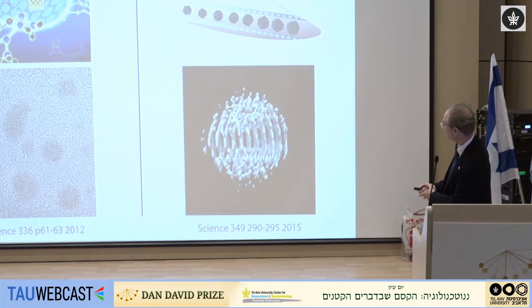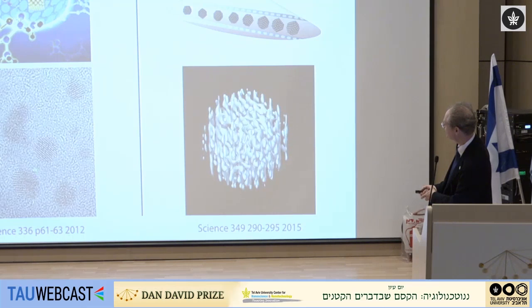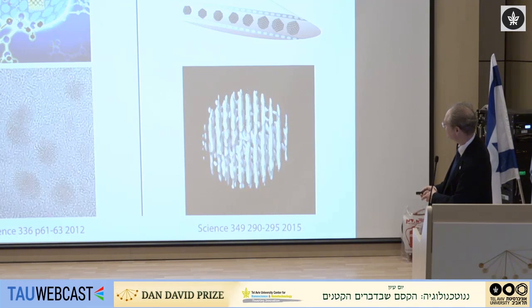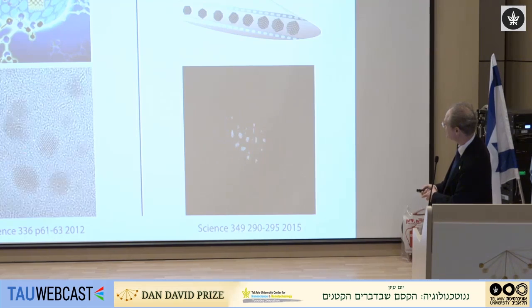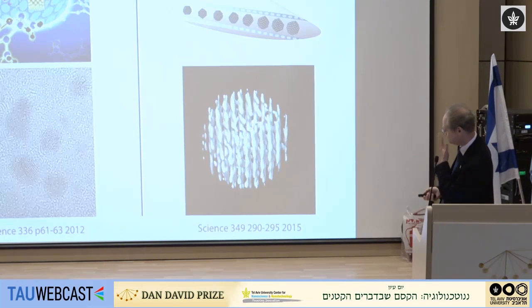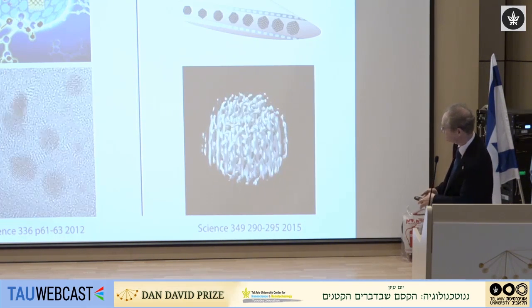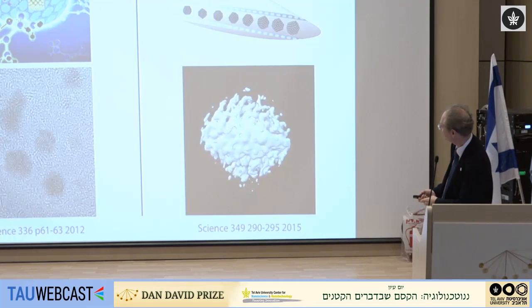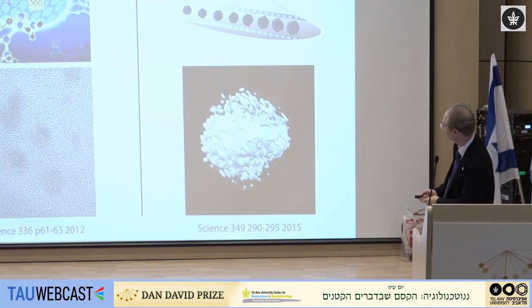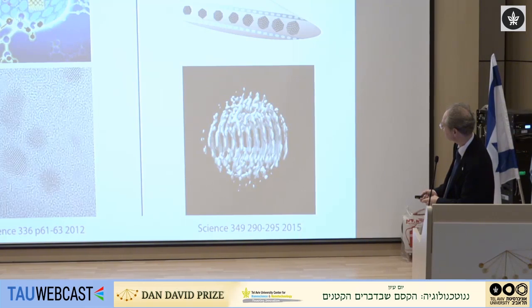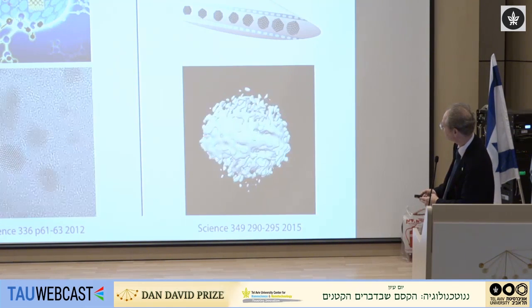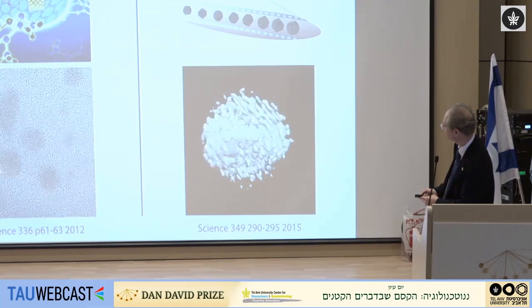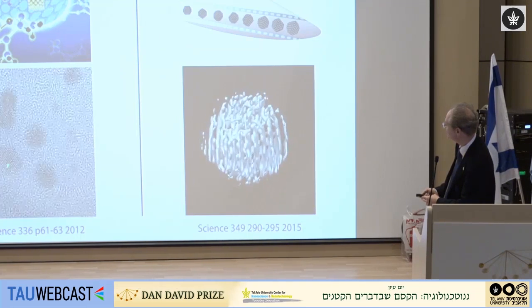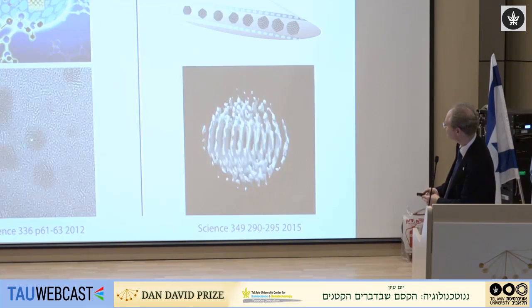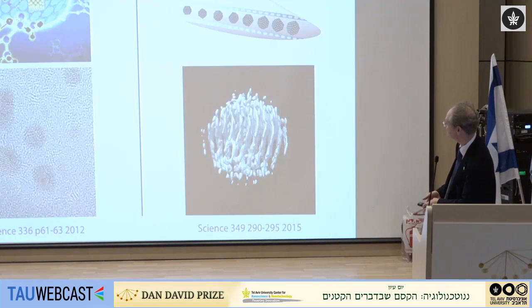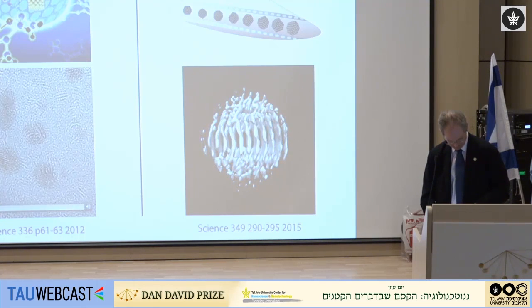So if you've watched this movie as it's been running here, it has to go back to the beginning and you'll see it again, but what you'll see is small crystals growing inside the liquid. I'll just give it a moment here to start over again. You'll see at the very beginning there's nothing there, and then the tiny crystals start to form. Or you can just see here the results of the final crystals. You can see that they have some lattice orientations, but also some defects inside them because they've been grown too fast, and we can't completely control that.